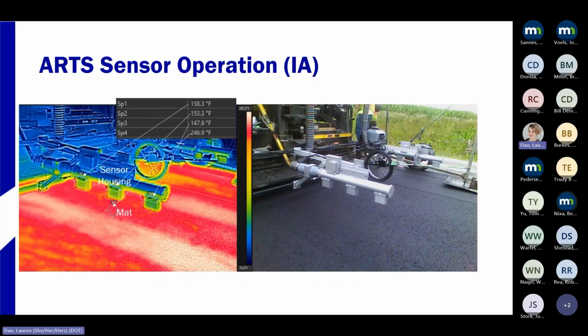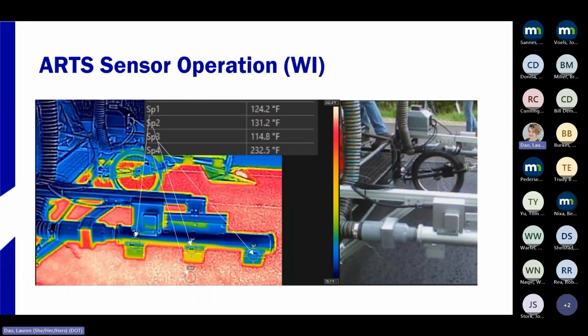So here is the sensor in operation in Iowa, and on the left side is a thermal image of the entire system, just to see how the temperatures are doing. You can see the asphalt is at like 250 degrees, whereas the sensor housing is close to 150 degrees. This is the temperature in the housing, and I'm told that the temperature at the sensor itself, close to the heat sink, is much lower than this.